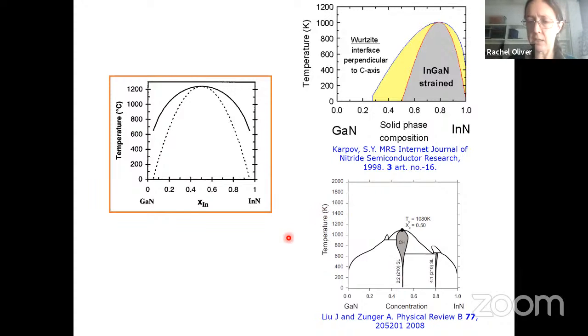Now, I'm not going to get into the details, particularly of what's going on down here with the sophisticated Liu and Zunger phase diagram. The key thing you need to know is the indium gallium nitride in the blue LED used in your LED light bulb is round about 20-ish% indium and is grown at around 700 to 750 degrees C. And if I mark that with my little blue LEDs on each of these phase diagrams, the Ho and Stringfellow phase diagram predicts you will get decomposition, but the other two phase diagrams predict that you won't, okay?